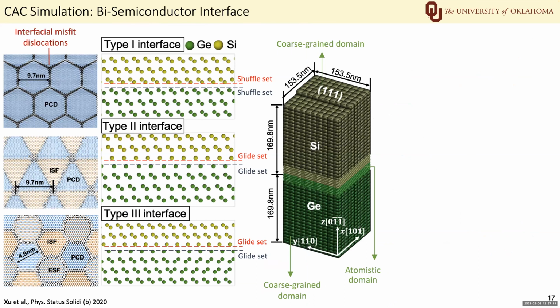In addition to metal, I also use the CAC to study semiconductors. Here is a silicon germanium bilayer. First, we find that there are 3 types of interfaces differing in interfacial misfit dislocation network. And all these 3 interfaces have been observed in experiment. Similar to the previous slide, we want to understand how the interaction mode differs among these three interfaces.